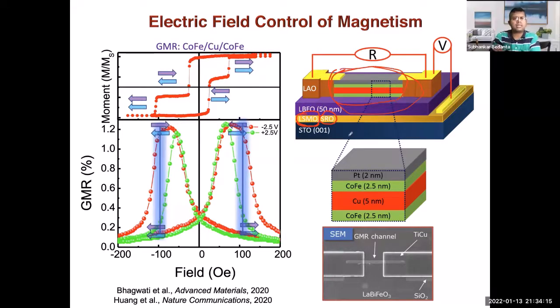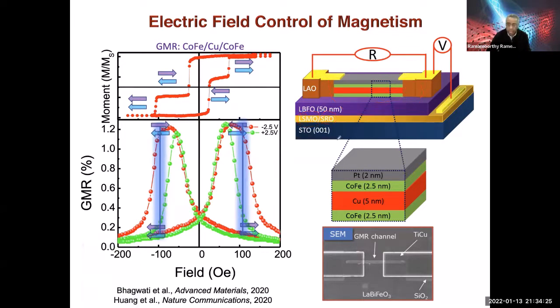So then why are these two cobalt iron layers having different coercivities? Great question. Again, I probably went through it very quickly. Thank you for asking me. The reason is this cobalt iron layer is exchange coupled to the LBFO. The LBFO is an antiferromagnet, a canted antiferromagnet. It's exchange coupled to the LBFO, and that coupling is given by this coercive field. It's about 100, 120 oersteds, while the free layer on the top is about 20 oersteds. Okay, thank you.